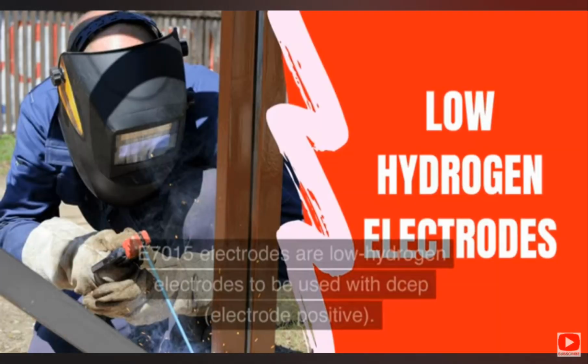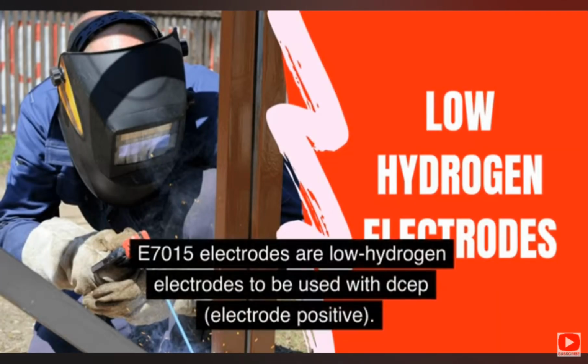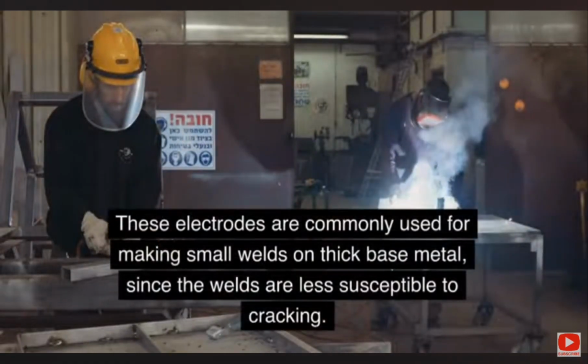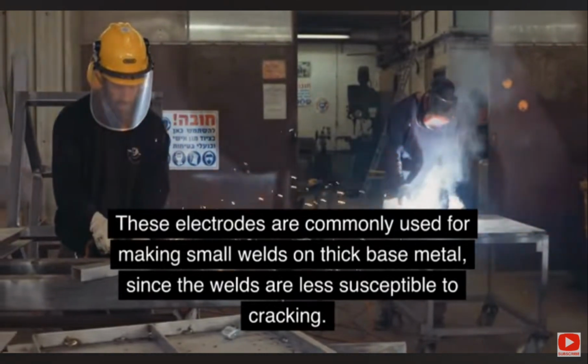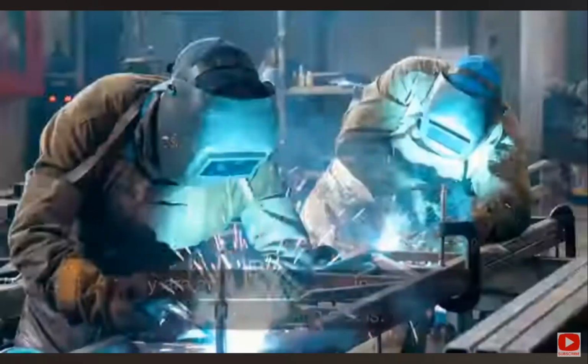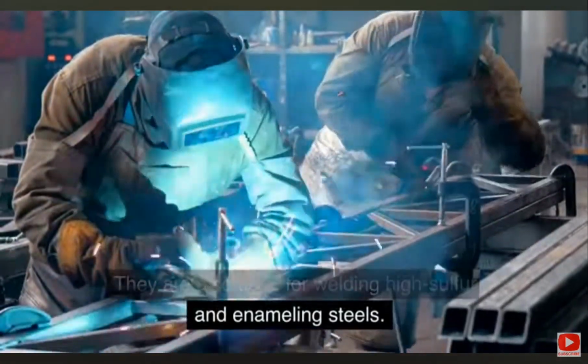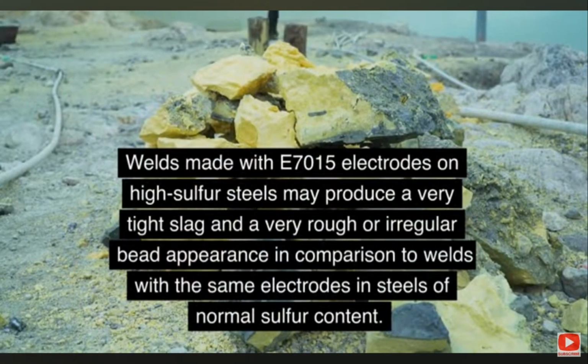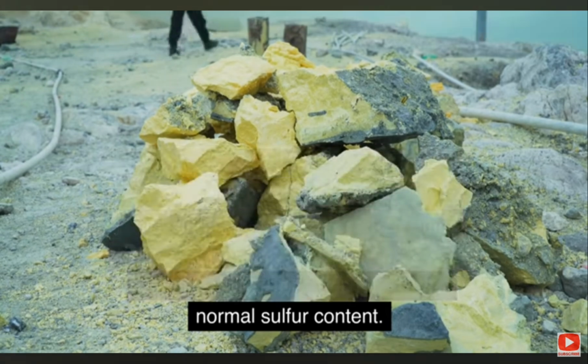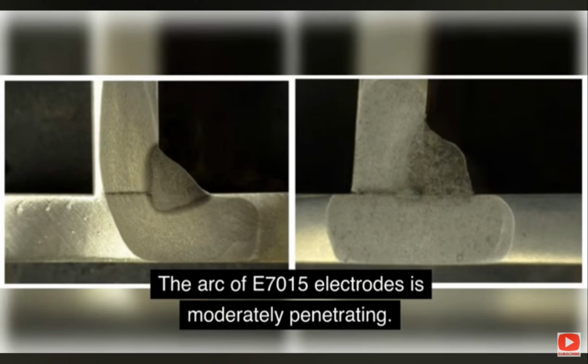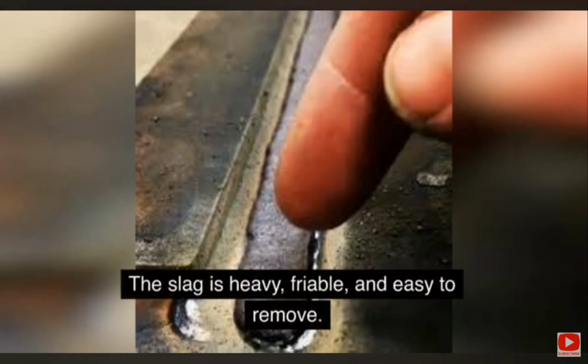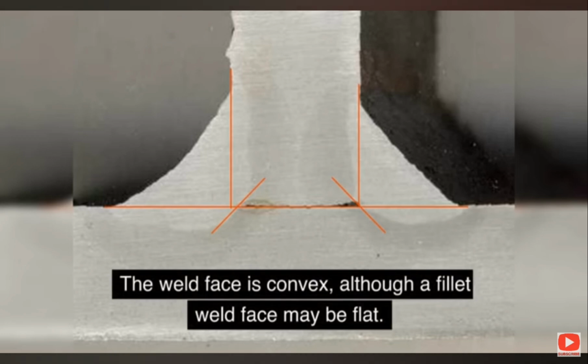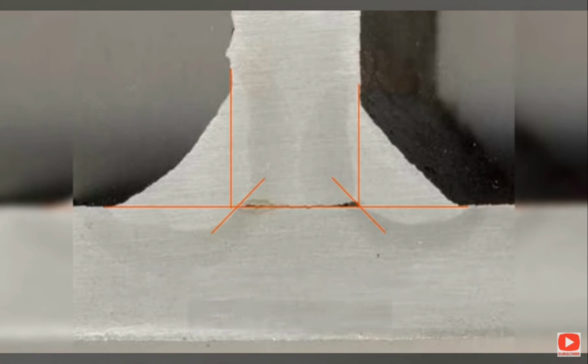E7015 welding rod. E7015 electrodes are low hydrogen electrodes to be used with DCEP, electrode positive. The slag is chemically basic. These electrodes are commonly used for making small welds on thick base metal, since the welds are less susceptible to cracking. They are also used for welding high sulfur and enameling steels. Welds made with E7015 electrodes on high sulfur steels may produce a very tight slag and a very rough or irregular bead appearance in comparison to welds with the same electrodes in steels of normal sulfur content. The arc of E7015 electrodes is moderately penetrating. The slag is heavy, friable, and easy to remove. The weld face is convex, although a fillet weld face may be flat.